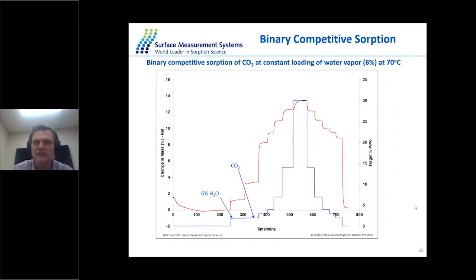If you look at other products, typically the vapor generation system is an add-on to your traditional BET measurements or nitrogen adsorption measurements. In that case, you might have some cold spots. Secondly, gravimetric systems, as I said, are designed to work at ambient or high temperatures, whereas volumetric systems historically were designed to work only at low temperatures, 77 Kelvin or 87 Kelvin. So I think the gravimetric system, or DVS Vacuum, is more beneficial for studying applications. Plus, when you do gas adsorption, it's also easier to measure, let's say, CO2 under vacuum in dynamic mode than in static mode.